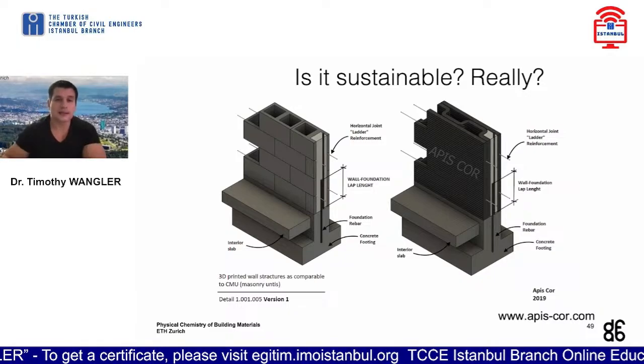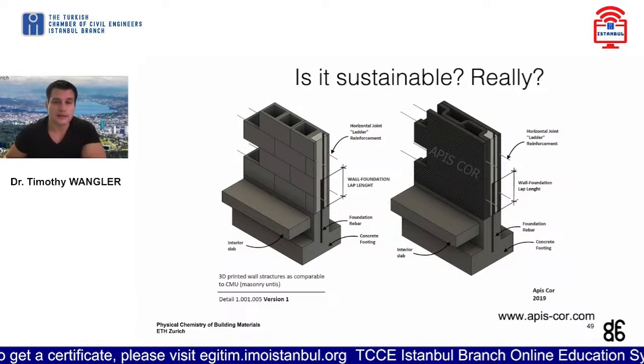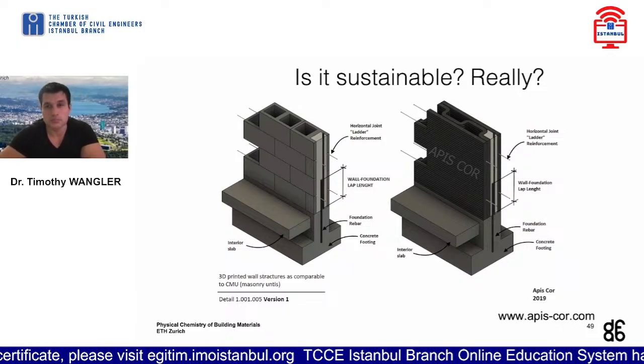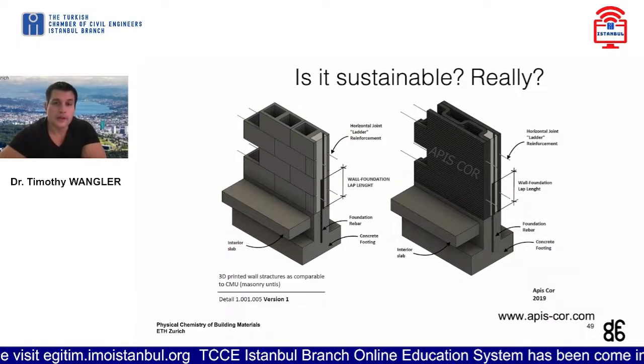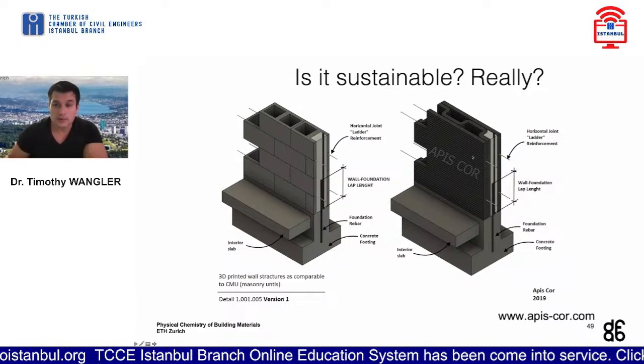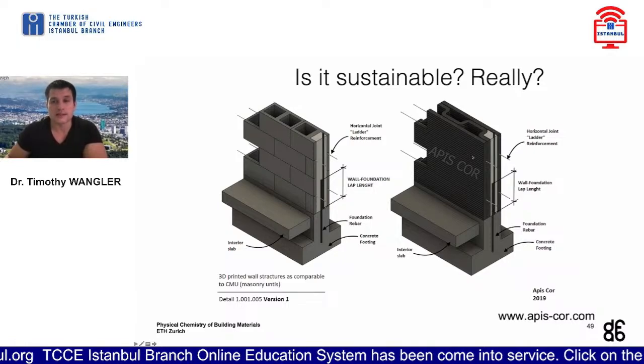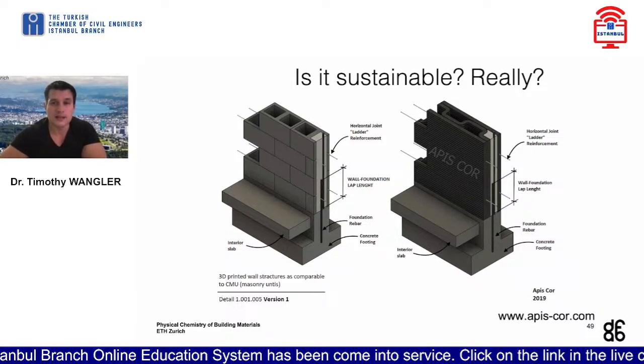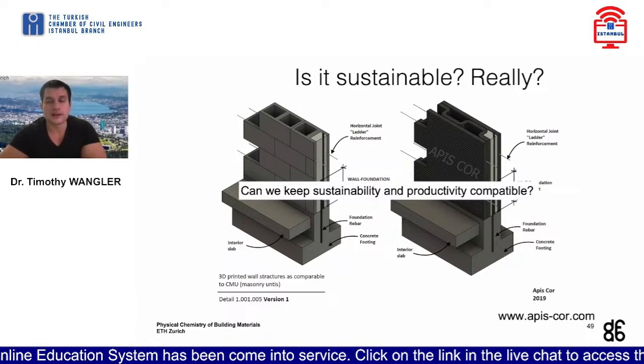And if you're replacing, so this is coming from the website of Apis Cor, which is one of the more major 3D printing players right now. They essentially propose here to replace concrete masonry with 3D printed concrete. And 3D printed concrete, as we saw, is on a per unit basis much worse than standard concretes in terms of the kilograms of cement that are being used. So it seems that sustainability and productivity are incompatible at the moment with this. But I believe that there are many chances for these to merge and to complement each other. And I think it's up to us in the research community to make sure that that happens.